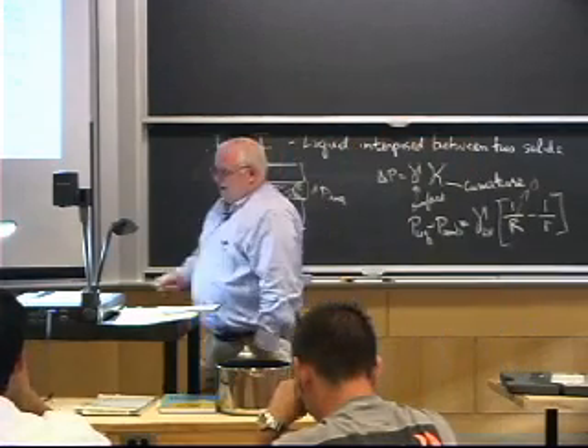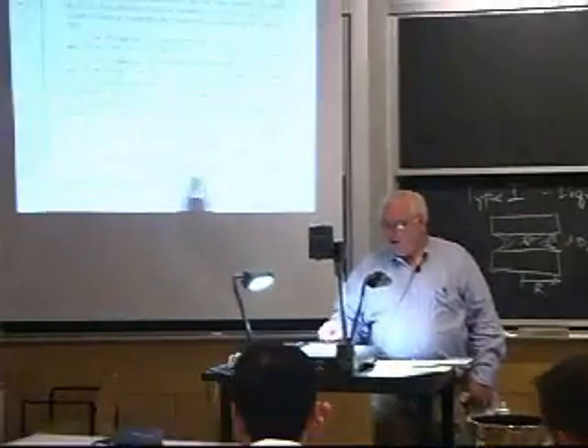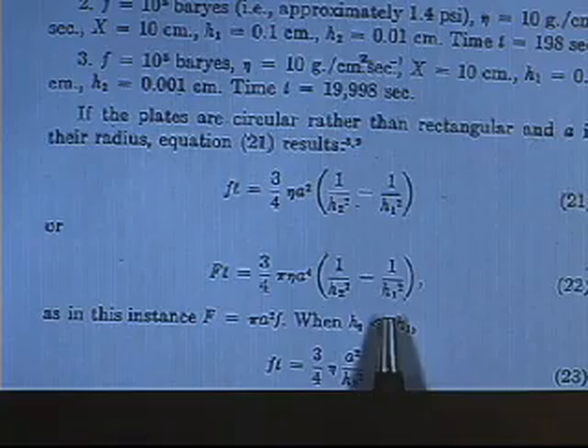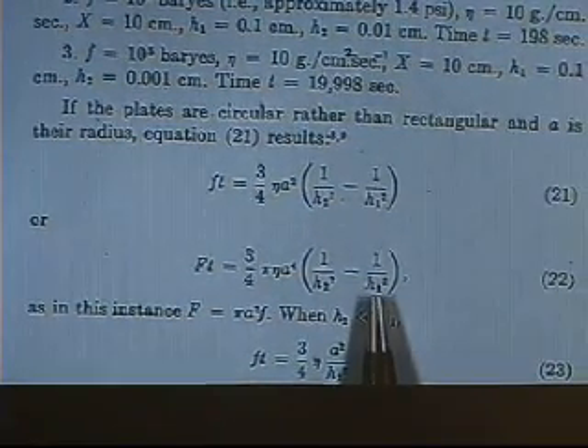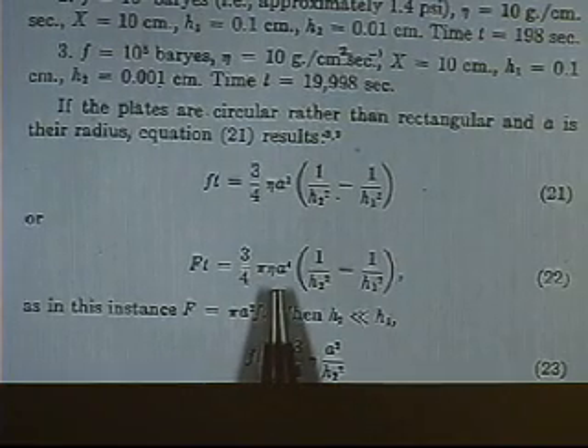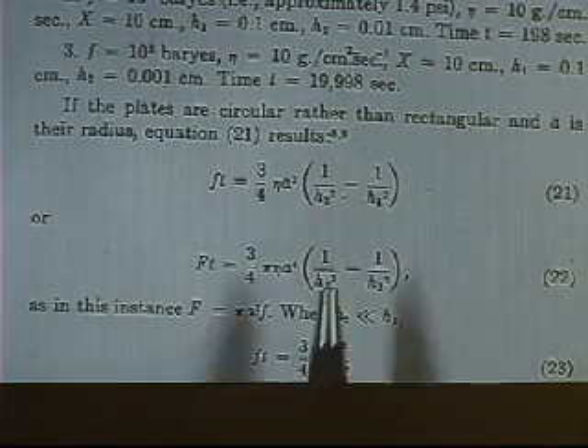The important term in the Stefan equation, there are two important terms. One is this final thickness, and the other, which dominates a lot more than the final thickness, is 1 over h squared. So if I make the thing 10 times thinner, I get 100 times the force time product. But if I solidify the adhesive and go from a liquid adhesive to a solid adhesive, I can get 10 orders of magnitude, not 2 orders of magnitude.